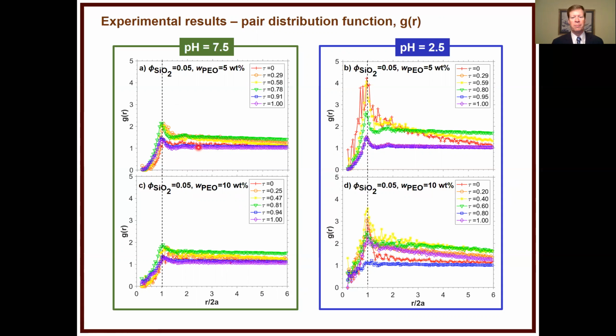And so on the right-hand side, it's harder to track these particles because number one, there's fewer in view, and number two, it's a disordered system. g(r) just simply isn't the best way to sample this. But you can see at later times, g(r) looks about the same, so that doesn't tell us much in this case. Essentially, g(r) is the same thing as you get from scattering. So with these subtle microstructure changes, you really can't back out the microstructure by scanning with some sort of scattering device as well as you could in this case. So let me show you some of the other data we can get.